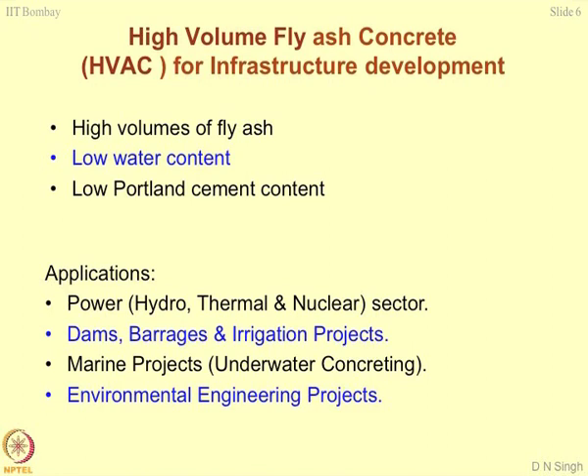Most applications of HVAC are found in the power industry — whether hydropower, thermal power, or nuclear power. Design of domes and shells of reactor buildings is where HVAC is preferred. You can use up to 50 percent fly ash by compacting it in a specialized manner. This is also where people started talking about self-compacting concrete. Most dams, barrages, and irrigation projects also use this type of concrete.